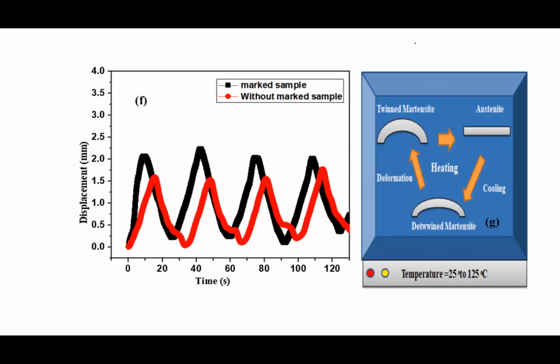With respect to marked and without marked samples, we could observe that the marked sample showed a better displacement as compared to the samples without marking. And the interesting part in this is that you don't need to go for post processing. Like in the earlier case, when we went for direct wire arc based additive manufacturing, we went for some kind of post processing. We may need to dice the sample and then do the actuation. Whereas in this case, after the laser marking, we can take the sample and do the actuation. Let me just show you a small video which shows how the actuation was performed.